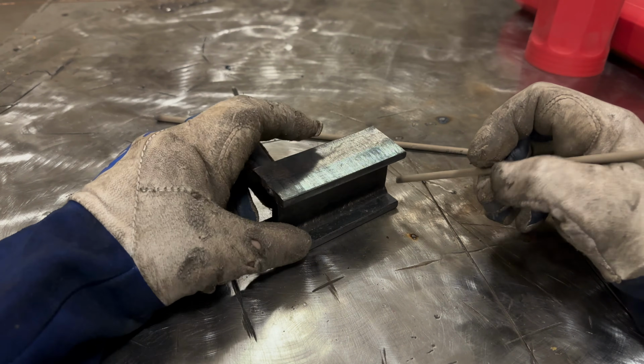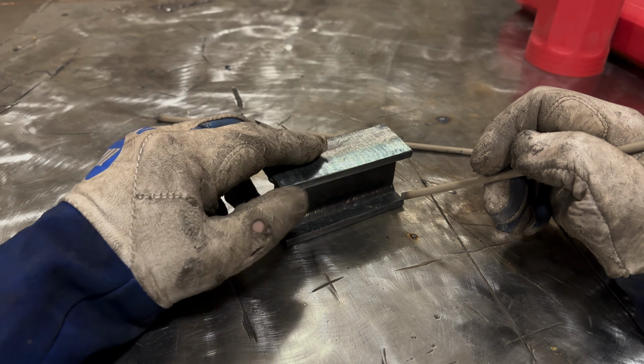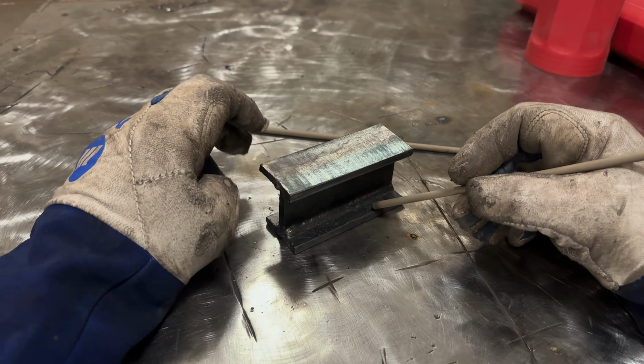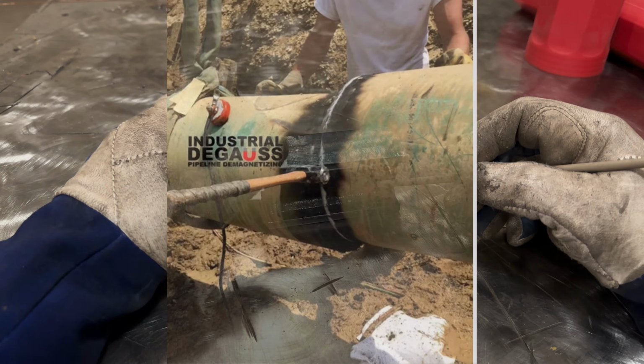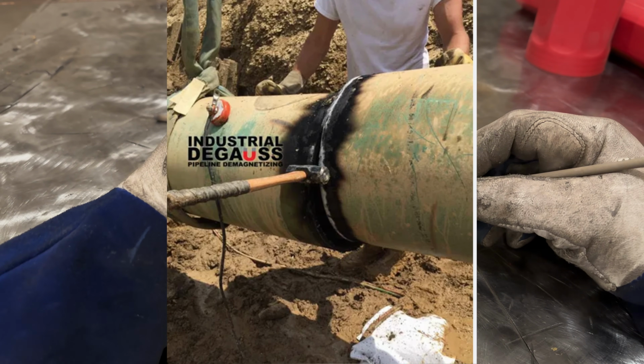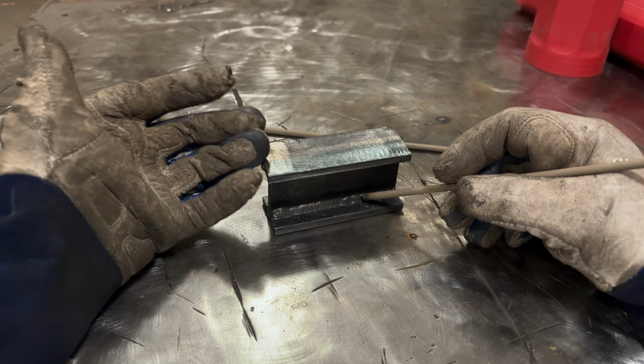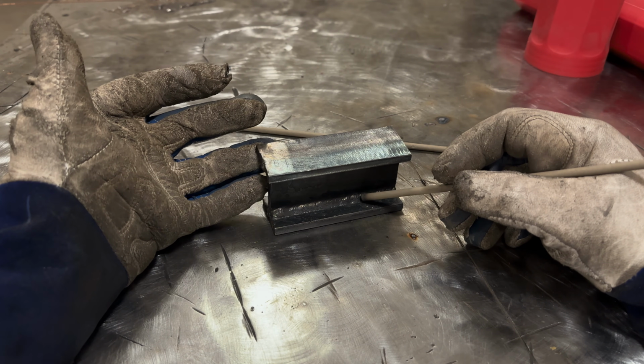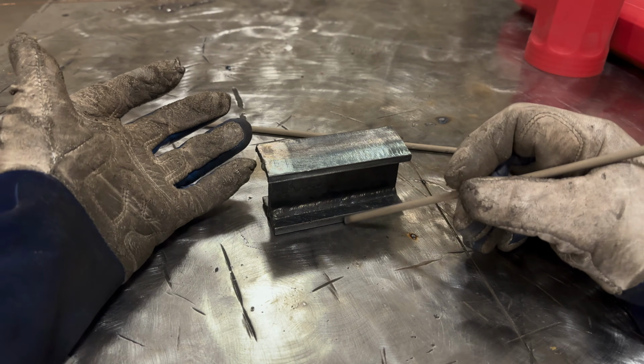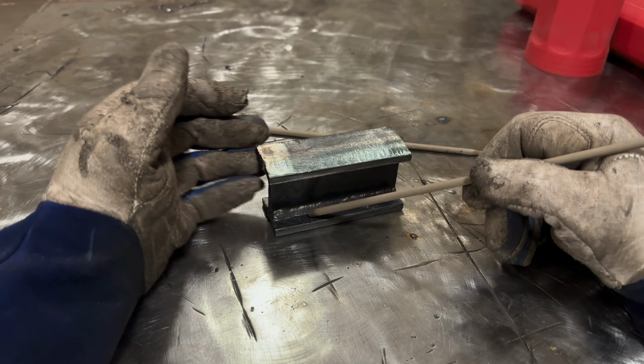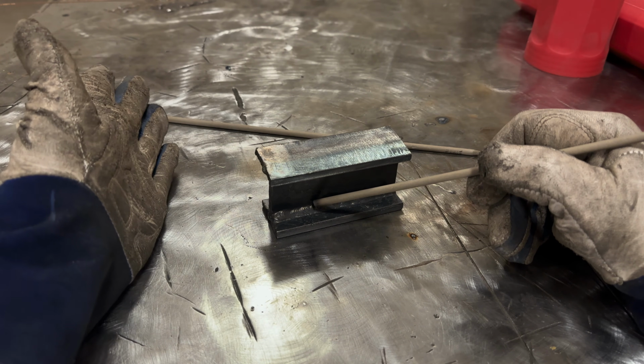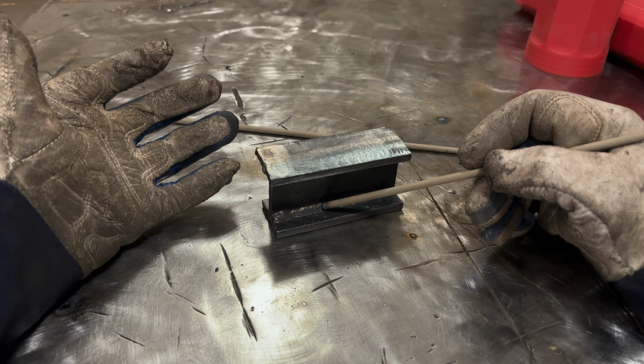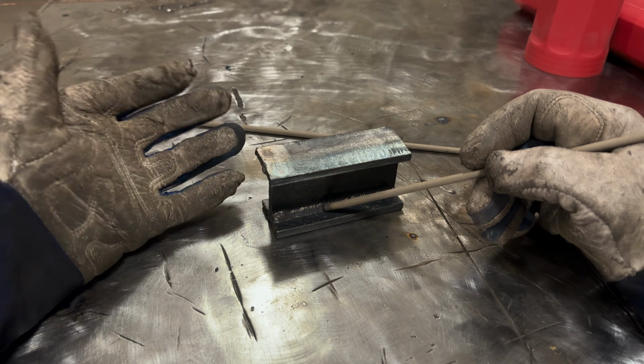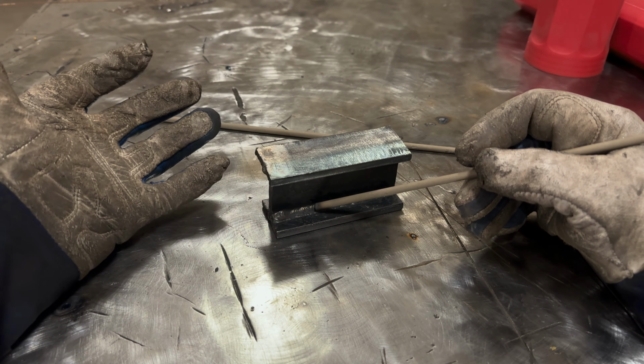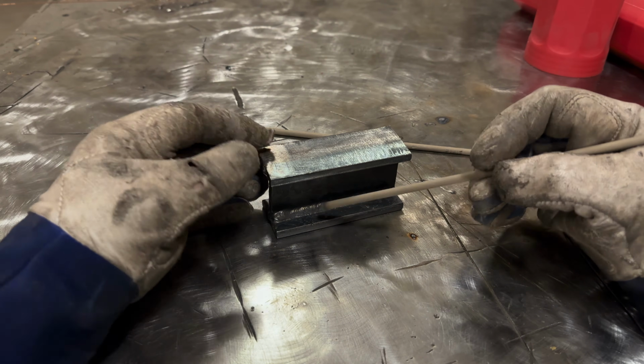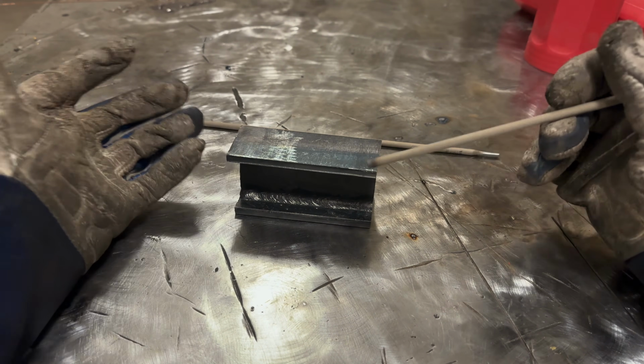Now, occasionally, you may weld on material that is magnetized. And that does happen. I've seen pictures of guys out in the pipeline fields where they literally can hang a 2 or 4 pound mallet off the end of a pipe that they're supposed to weld on. Well, you can imagine the effect that could have on an arc. If it's strong enough to hold a 4 pound sledge on the pipe, or even a pickaxe I've seen, you can imagine that arc is going to have a very hard time being stable. If you try and weld on a straight up magnet, good luck. You just got to do what you got to do, I guess, and the weld quality is going to suffer. Not that you generally weld on a magnet, but you get the idea.